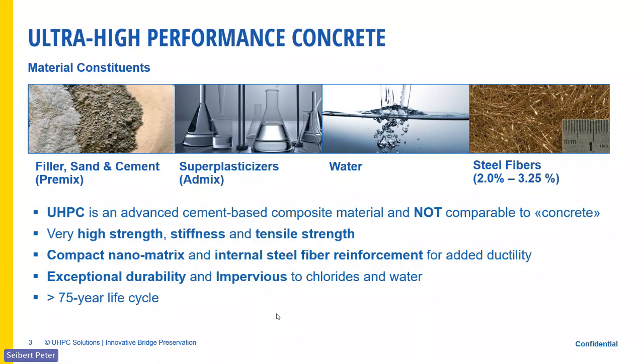As a fun fact too, if you compare that to a regular concrete with 3/4 inch stone, sand, and cement, and the number 4 rebar, if you would scale that diameter down from that number 4 rebar to the diameter of this fiber, you pretty much have the same aggregate size, which would be a 3/4 inch in regular concrete, as well as the finest particle in here, which would be a silica sand, which is around 500 to 600 microns. So it's a micro reinforced concrete, more or less.